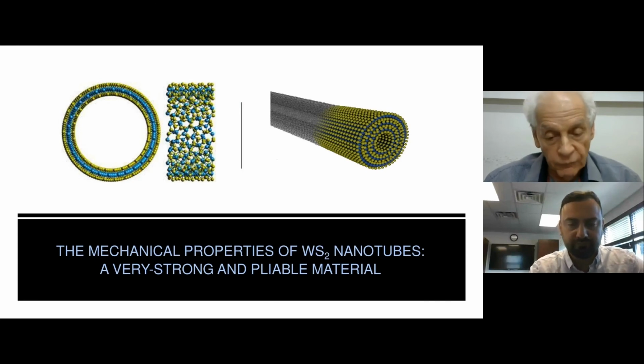First of all, the sulfur, the outermost, you must understand that the surface is always sulfur in this case, and the sulfur is negatively polarized. So you have already some kind of negative polarization, dipole. But then, of course, also, because these materials are synthesized at elevated temperature, there will always be sulfur vacancies.